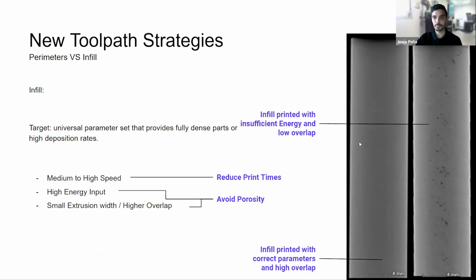And this is another example of the tomography. In here, you can see the target that we are having, also the infill printed with insufficient energy density, and also on the left side, you can see the part that is fully dense. How can I correct the problem that I am having in the right side picture? So with medium to high speed, I can have minor defects. Let's say that I want to have a deposition rate of, I don't know, a kilo, to say something. So depending on my energy density, I will have one result or another. I'm not going to be able to get, let's say, zero porosity if I don't control my energy density further than the bands that we discussed before.